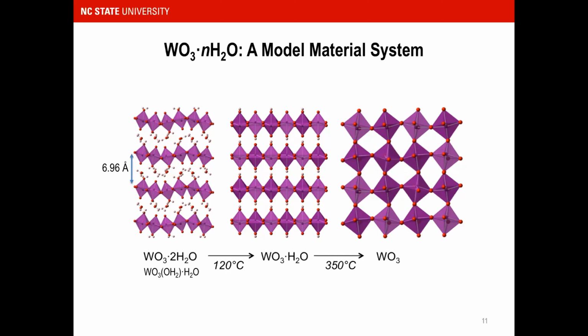And if you do that, you get this dihydrate structure, which is a layered material of corner-sharing tungsten oxygen octahedra, separated by about 7 angstroms. And you have 2 types of water molecules: a lattice water that's just loosely bound within the interlayer, and a water of coordination that's actually directly coordinated to a tungsten. So these octahedra are highly distorted.